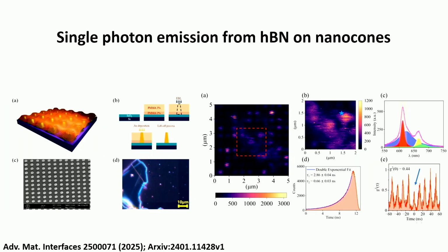So again, this is hBN. This is hexagonal boron nitride. So this is on top of these gold discs. So we showed that we can get single photon emission from these structures. Again, the strain engineering is possible in this. You don't need an AFM tip or complicated design. So you just make these, and around these nanoparticles, because of the undulation, there is a strain in the structure which changes the wavelength, and also you can control the stress and strain, so that you can control the emission from these structures.